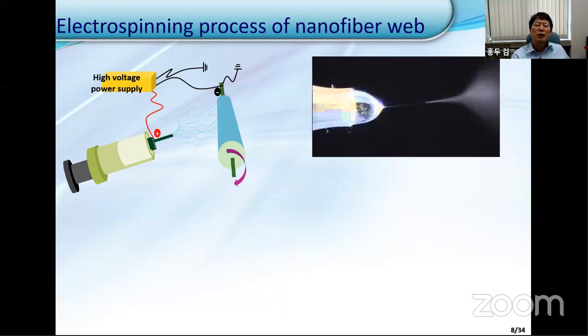So instead of just a regular film, for my experiment, I'm using a nanofiber web made by the electrospinning process. To make this nanofiber web, you simply dissolve the polymers in a good solvent, and then apply a high voltage on the needle, and the collector side is just grounded. Then you apply about a kilovolt or more, sometimes 10 or 20 kilovolts in certain cases. It depends on geometry.